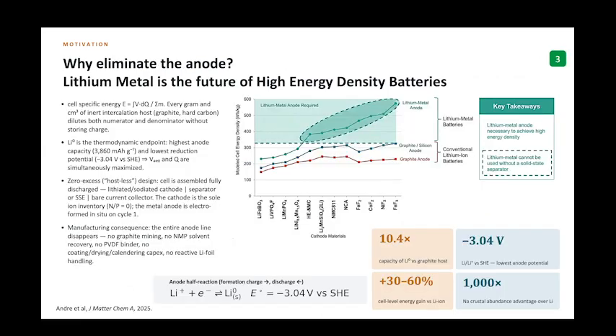As every gram and every square centimeter of the battery's volume matters, by removing one component like the anode, we can get lots of benefits. As you can see on the anode half reaction on the bottom side, what we need is to store lithium. And the lithium source in conventional batteries is the anode. But what if we ship the batteries with the cathode holding all the lithium, fully discharged, so it can handle the whole cyclic behavior of the battery over cycles? This can lead to even 10 times better capacity compared to graphite hosts and 30 to 60% more cell-level energy gain.